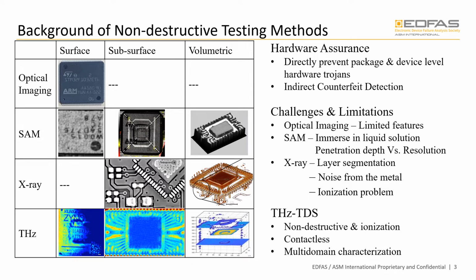Also, there's a strong trade-off that should be noted between the frequency, penetration depth, and the resolution. So this means that penetration through thick, heterogeneous integrated packaging will require it to go through more layers and may have overall a lower resolution.